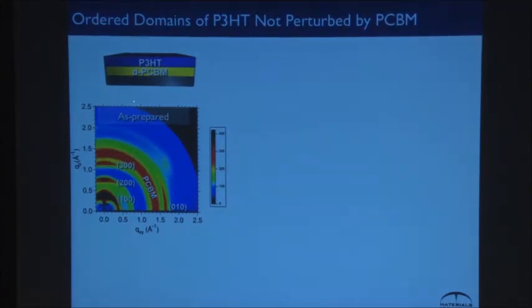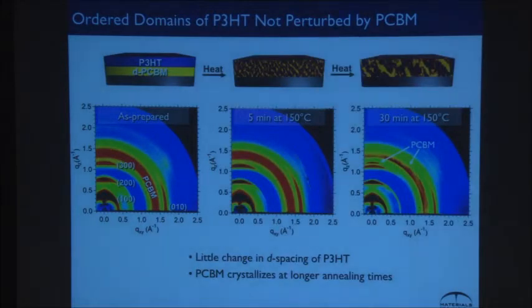It's kind of nice. We go to the synchrotron at Stanford, and we make a bilayer like this, and we say, well, everyone said that the fullerene will impede the P3HT crystallization. But as we heat this thing up, the P3HT polymer just doesn't care very much. It just keeps crystallizing like it wants, doesn't change structure. The fullerene, you go from this bilayer to something that's fully mixed, and then eventually you heat it long enough, and the PCBM decides to crystallize and make big crystals.